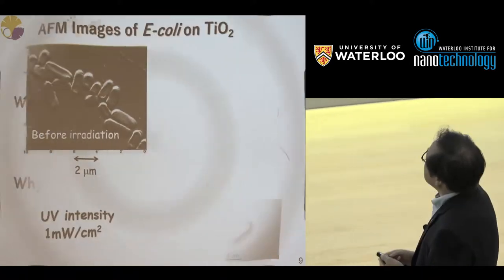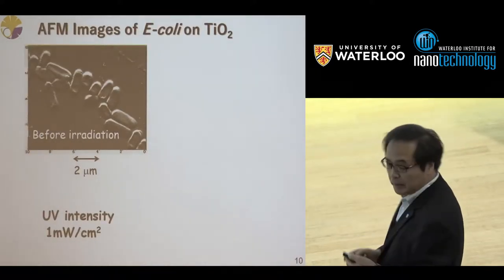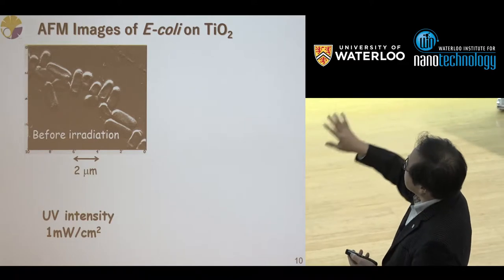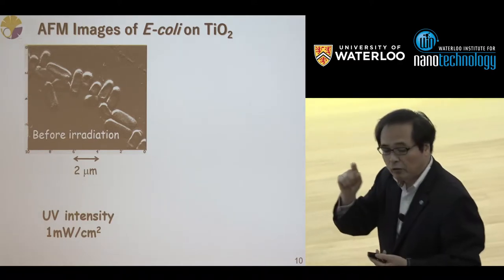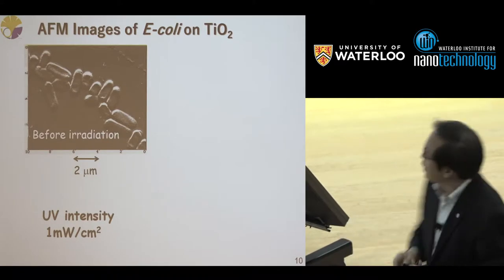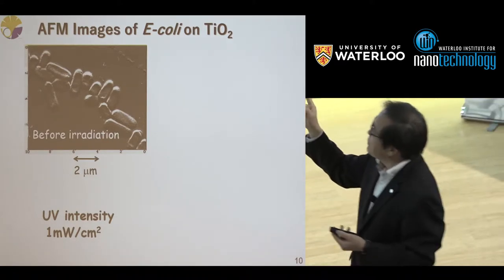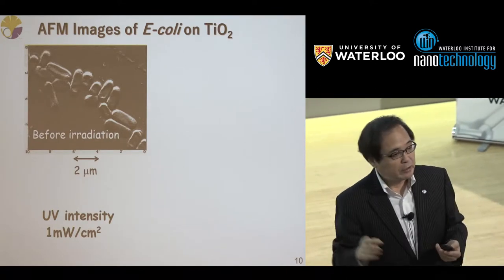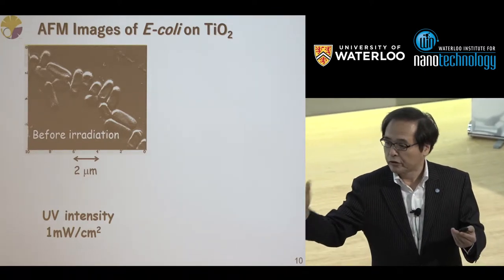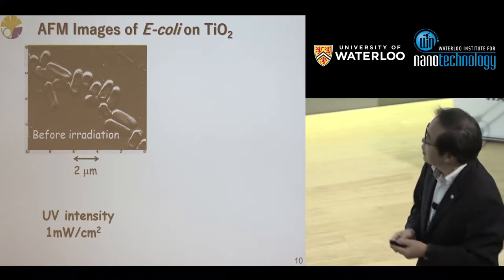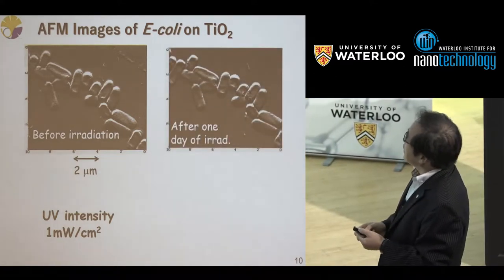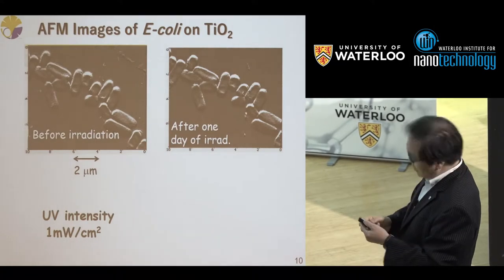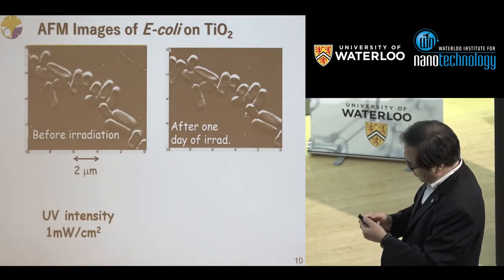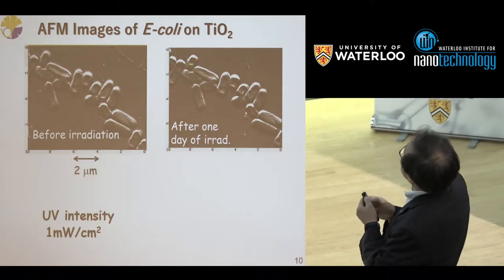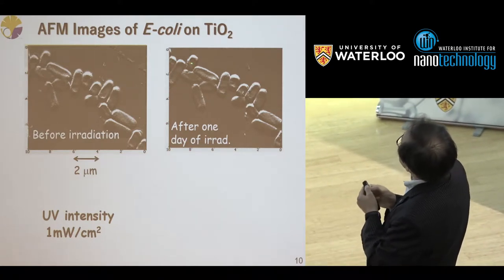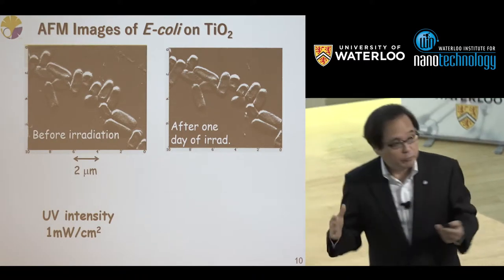Okay, so this is the AFM picture of bacteria on titanium dioxide surface. The size of bacteria is 1 micron, 2 microns, or something like that. And the UV light intensity in this case is 1 milliwatt per square centimeter. This one is the average outdoors UV light intensity. After one day irradiation, it seems not to be changed, but actually when we see carefully, the outer membrane we can see here has disappeared. So the outer membrane is already decomposed.